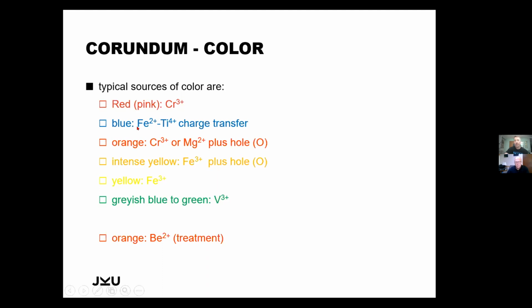The blue is generally created by iron 2 titanium 4 charge transfer. In this case, it's important to see that this is much more potent as it only needs a couple of ppm. Only parts per million of titanium and iron need to be present in order to have this color mechanism. You always have iron 2, iron 3 charge transfer, which is at 880 nanometers. This can be used, for example, to differentiate between the metamorphic sapphires and the other sapphires. Some have a high amount of iron, some have a low amount of iron. We have orange sapphires, which are due to chromium in many cases, but might also be magnesium.